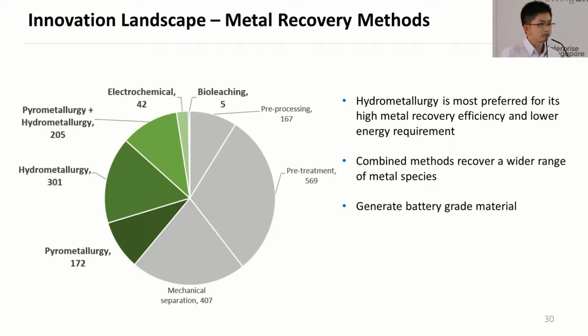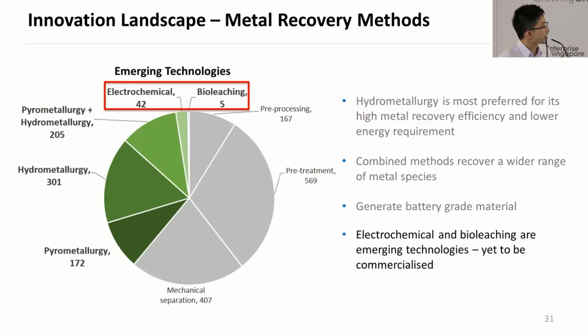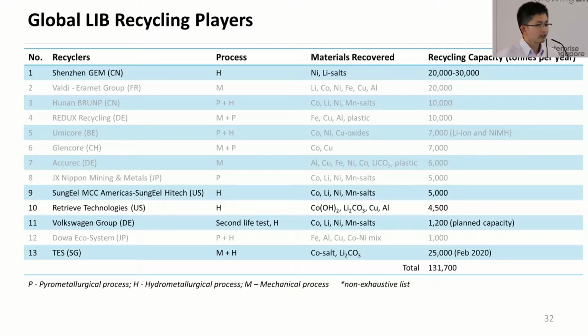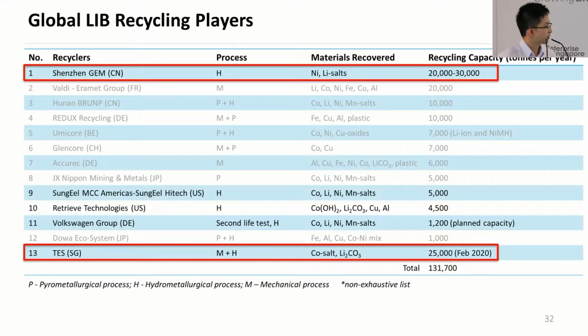From our patent landscape study, we have also uncovered 2 key emerging technologies. So they are electrochemical as well as bioleaching. But we noted that they are yet to be commercialized because most of the patents were filed by research institutions at this point. So here I highlight a list of players who focus on the hydrometallurgy process. So Shenzhen GEM, they are one of the largest recyclers in China. So they focus on the hydrometallurgy process. And then 2 days ago, we got news that TES, based in Singapore, is also opening up a plant. It's up to 25,000 tons per year processing capacity in February 2020. So what they recover here is cobalt as well as lithium carbonate salts, which is the precursor material for new battery manufacturing.